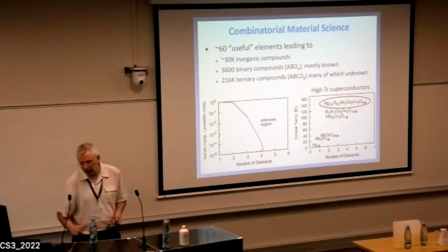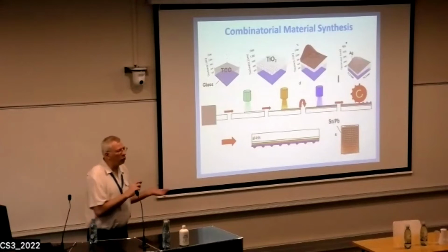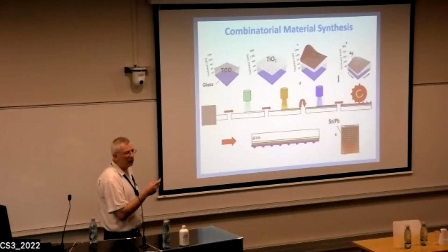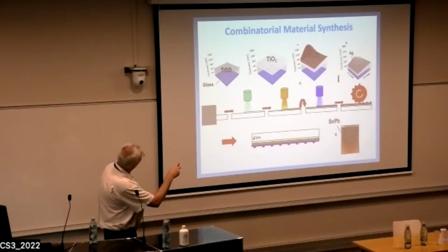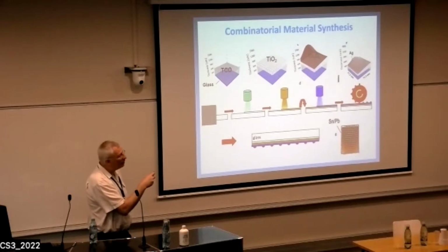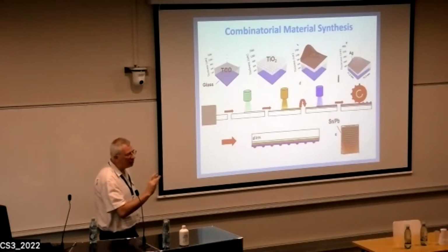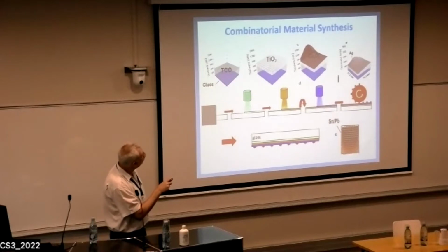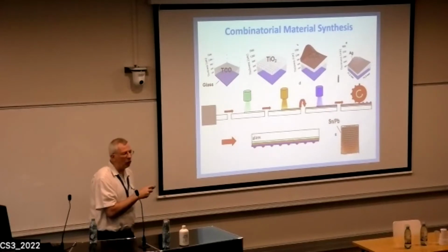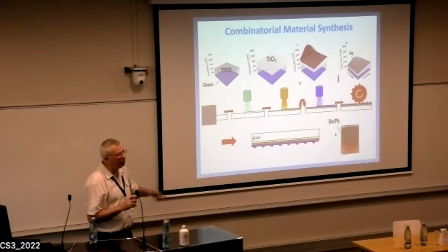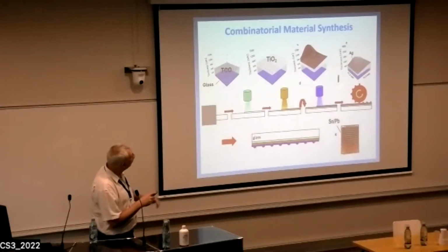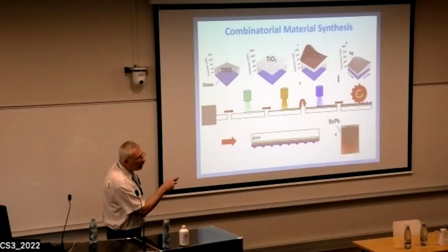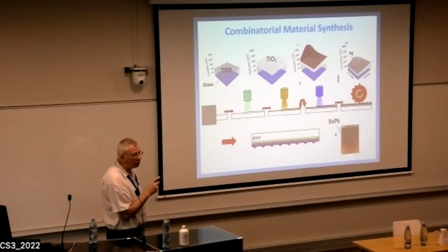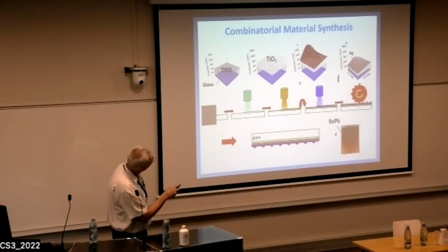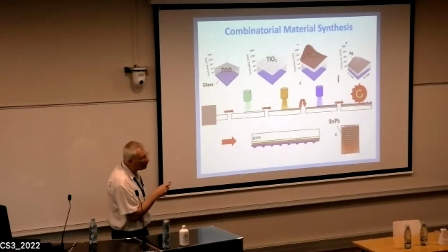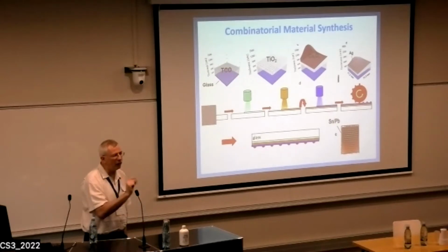How do you do it in practice? Well, we don't, but our collaborators do. So it's very easy, actually, at least for me, because I don't do it. You take a piece of glass, you coat it with a transparent layer, and you then deposit on it several layers of metal oxide. However, you don't deposit it in a regular manner, but rather with a gradient. And when you make 2 or 3 or 4 deposits, you get to a situation that each point on this glass has a different ratio of different metal oxides.